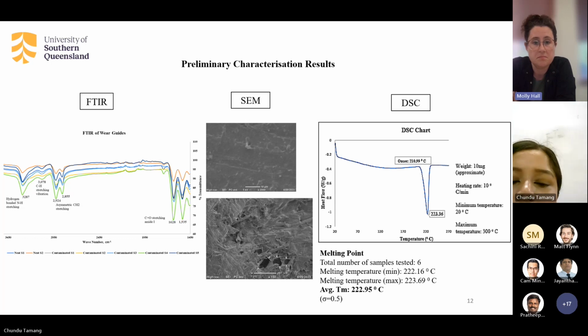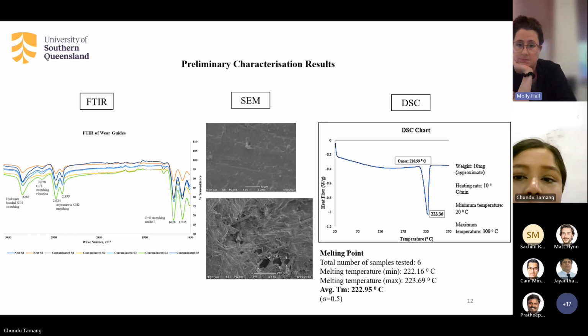Finally, in the DSC test, a total of 6 samples were tested. The minimum melting temperature recorded was 222.16 degrees Celsius. The maximum melting temperature recorded was 223.69 degrees Celsius, with the average melting temperature of 222.95, which was pretty consistent for both the used and the neat samples. So again, these were just the preparatory tests and results, and the guides collected were not sorted according to their location of installation. So these results are not very comprehensive.